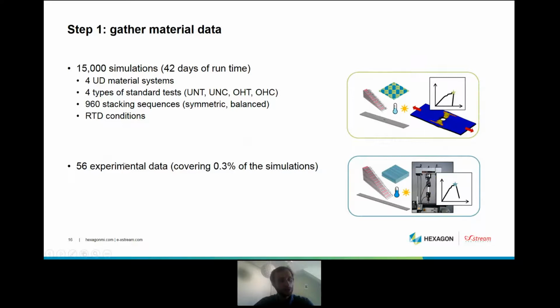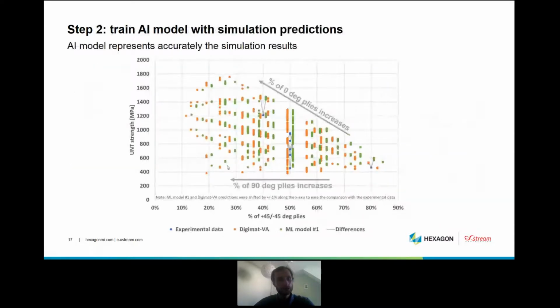On top of this, we added 56 experimental data points from the literature, so only 0.3% of the simulation points. And with this, we started training the AI model. So first, what we do is that we train an AI model with solely the simulation predictions.